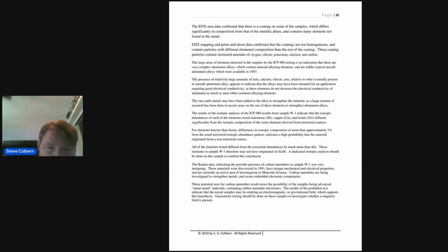The sheer number of elements in the material was very, very strange and indicates they were very unusual. And the rare earths, you usually don't see that in aluminum. They're very strange samples, but I was just kind of surprised that they weren't ultra strong or didn't have other unusual mechanical properties. But then again, we don't know that they don't under certain conditions. We need to do more testing. There's a lot of this material available. Mr. Wade has at least a couple pounds remaining of this material, I'm pretty sure.